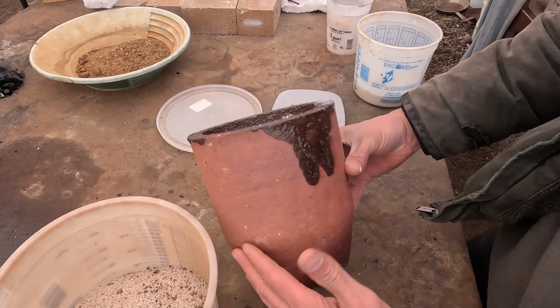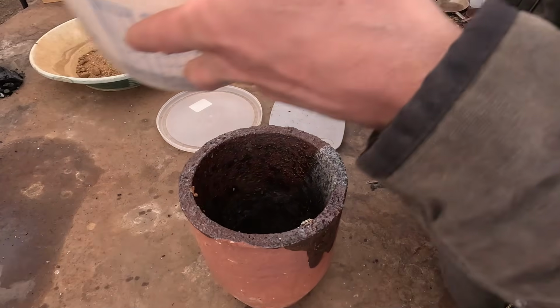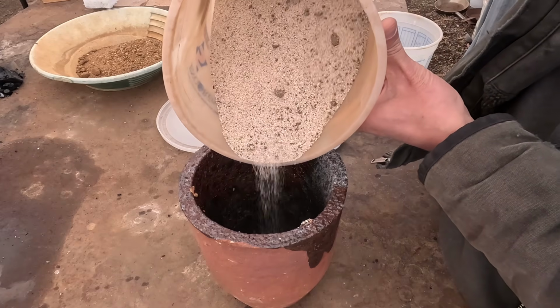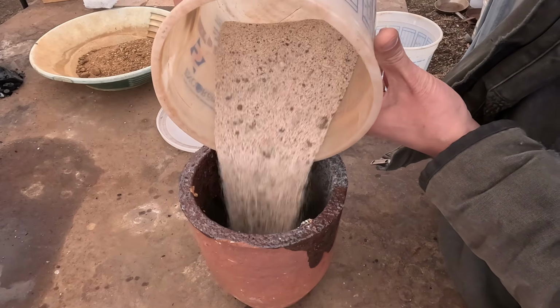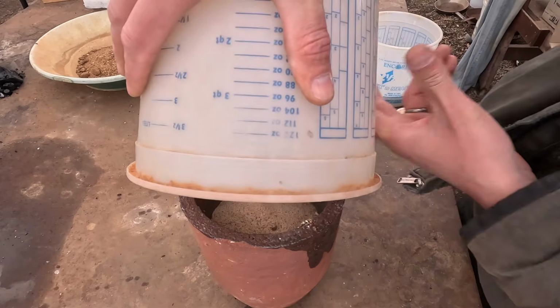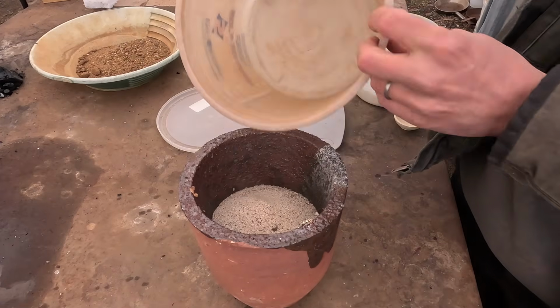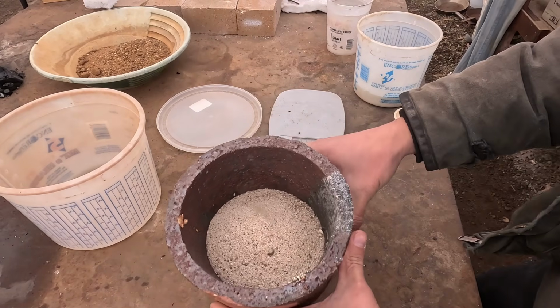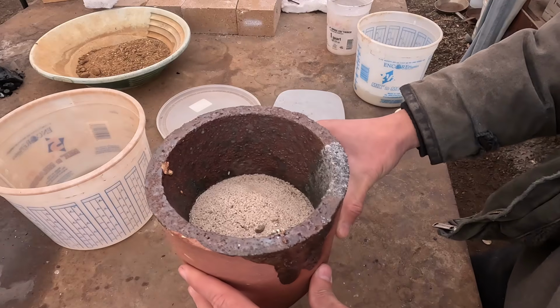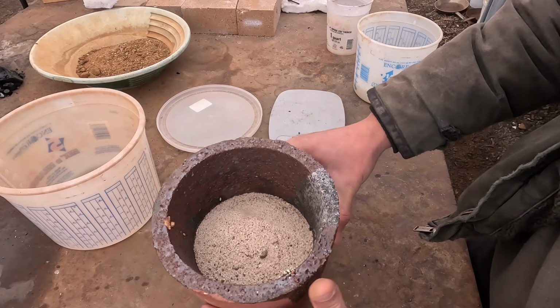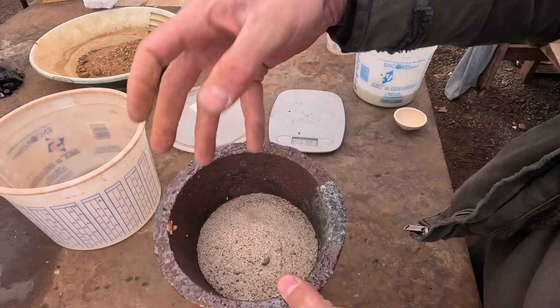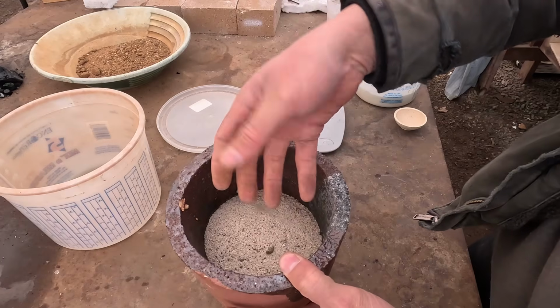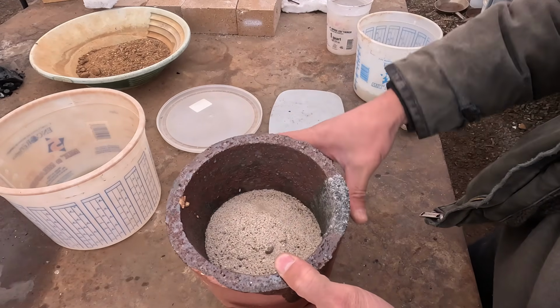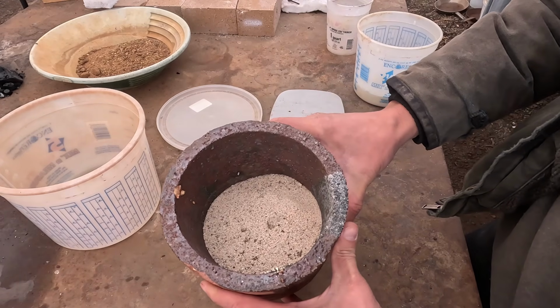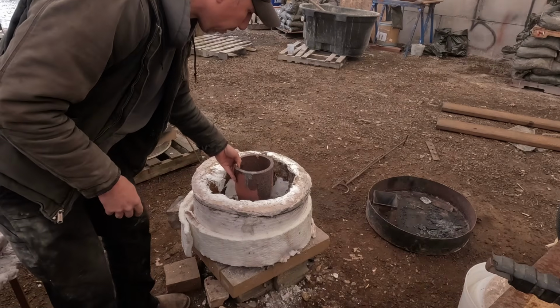This is a number 10 crucible. I'm hoping all this will fit in there with enough room for the oxidizer. Oh yeah, perfect. Usually want them about half to 3/4 full. So that's maybe half or a little bit more. And as this thing heats up, gases will be released, and sometimes it foams and bubbles, so it'll gain some volume, but that should be plenty of room in there for our smelt. We'll put it in our sad little furnace here.